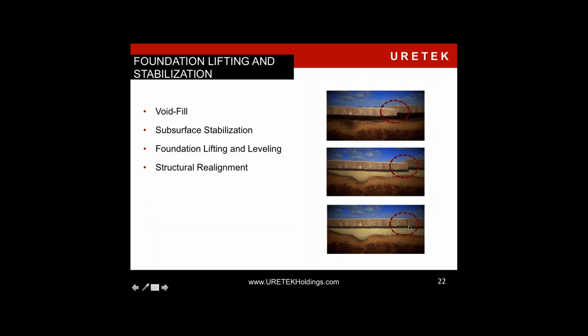The big point I want to make here is that a lot of the testing has shown that at this joint, once you have stabilized and void filled, you now have excellent load transfer. So in warehousing, manufacturing, where you have forklifts running back and forth, you have excellent load transfer from this panel to this panel by using the high-density polyurethane. And under vibratory loads and the constant impact of traffic, the high-density polyurethane will stay intact.